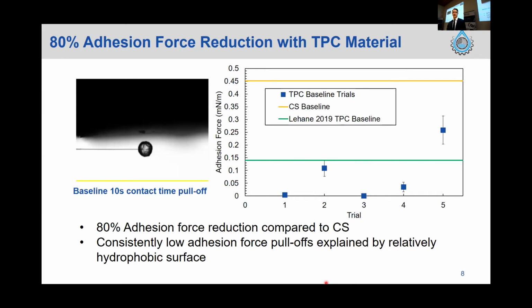So just to walk you through what this figure is here, on the vertical axis we have the adhesion force, which is in millinewtons per meter, and just each of the trials here labeled. So for each trial there was a new hydrate particle that was nucleated, and basically what each data point there shows is the blue is the mean, with a 95% confidence interval also shown. And along with that is the mean baseline for carbon steel.